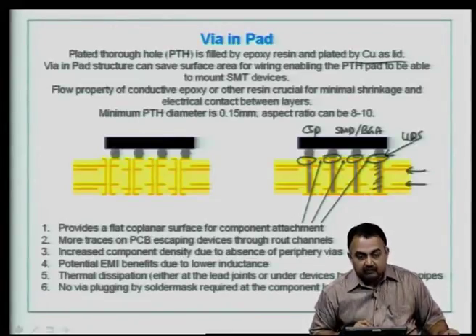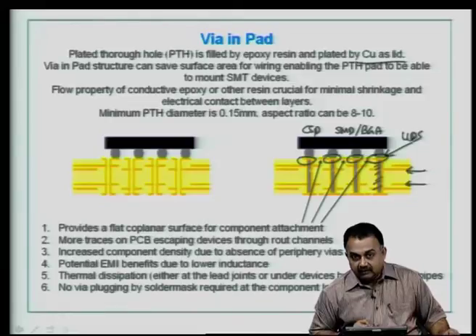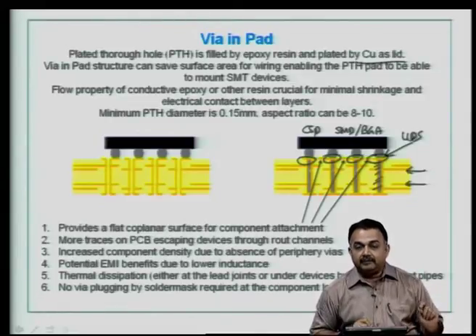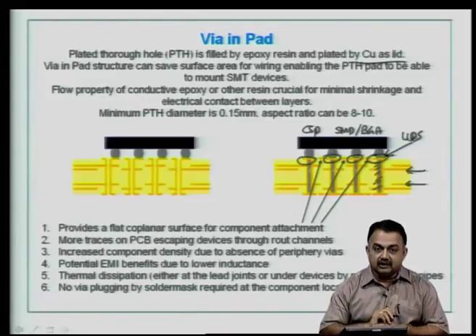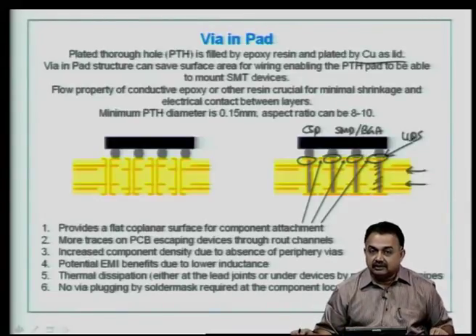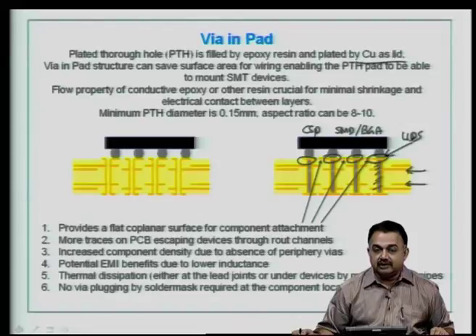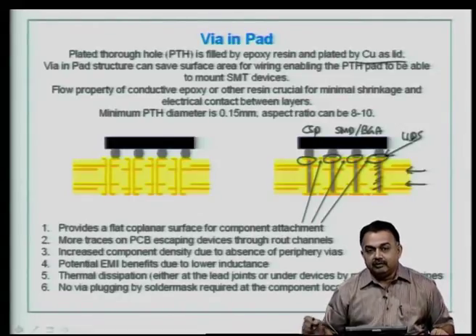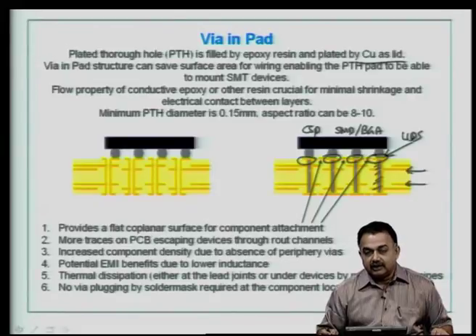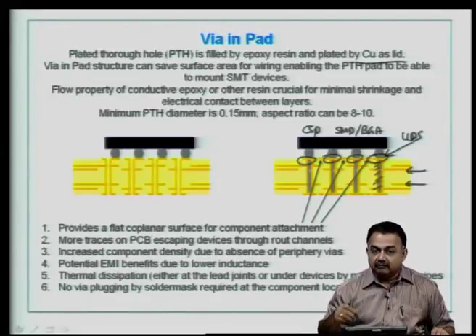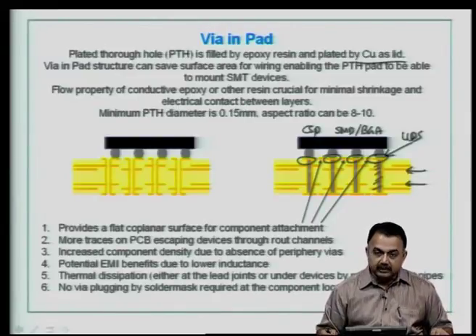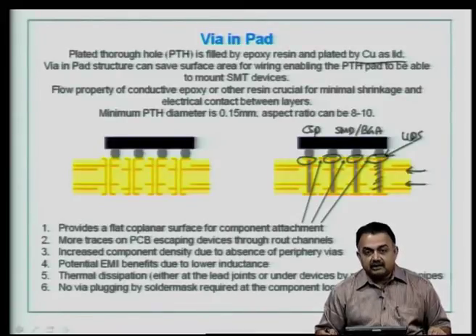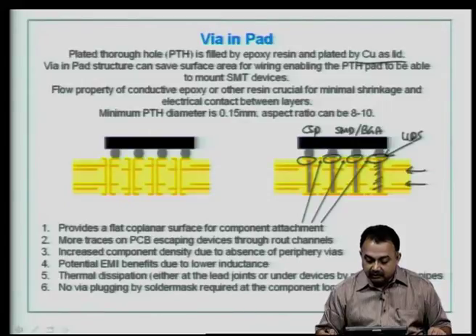Minimum PTH diameter is about 150 micron, aspect ratio can be 8 to 10. You can work with this aspect ratio in this process because you are not doing electrolysis plating, you are simply filling it. The aspect ratio in these cases can be an issue if you are using a wet process like an electrolysis process, because you need to ensure that your liquid, that is your electrolyte in the electrolysis copper plating bath, wets through the micro holes and then provides a very good even thickness of copper. That can be done by micro sectioning, but rather than going through that route, you can work with the filling of the via.